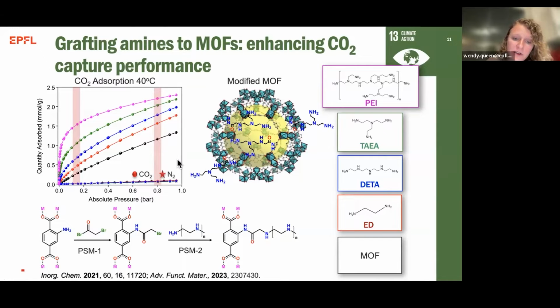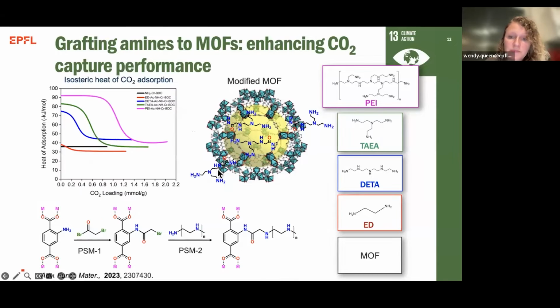Now let's look at what it does to the nitrogen. Here you can see the amount of nitrogen at about 0.8 bar, which is the partial pressure of nitrogen in post-combustion flue gas. You can see that it actually absorbs very little nitrogen. As a result, this gives rise to high CO2 over nitrogen selectivities. So the parent material is less than 20, and you can see that when we modify this with various amines, particularly the polyethyleneimine, we get to selectivities over 400. The reason is because we're enhancing the amount of CO2 it absorbs, but we're also decreasing at the same time the amount of nitrogen that the material absorbs.